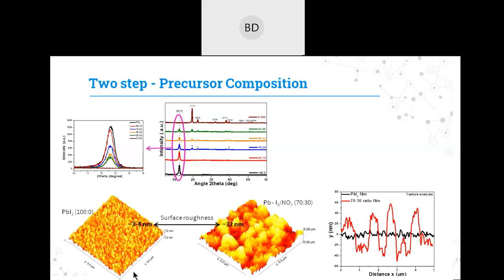If you see from the atomic force microscopic images, the lead iodide, which is pure and doesn't have any lead nitrate concentrations, shows a roughness of around 3 to 4 nanometers, whereas this one shows a roughness of around 30 to 35 nanometers. So if the roughness of the PbI2 is higher, then it will have more active sites so that the MAI can penetrate better into the PbI2 structure, and it can give a better conversion. If you see in the texture analysis, the texture of this film has a lot of ups and downs, which shows a lot of active sites present from different directions for the conversion.